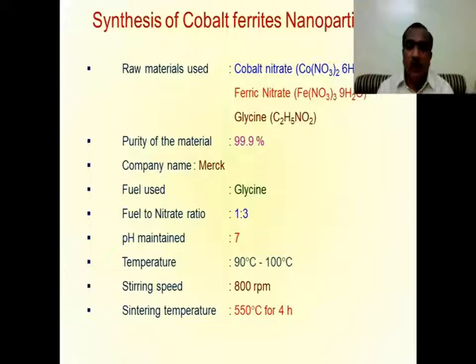We prepare this cobalt ferrite in nanoscale dimension by using the Sol-Gel autocombustion method. There are different methods for the preparation of cobalt ferrite nanoparticles. There are wet chemical methods like chemical co-precipitation, microemulsion, Sol-Gel, etc. Sol-Gel autocombustion is one of the best techniques for the preparation of nanoparticles of ferrite. The raw materials used in this synthesis method are cobalt nitrate, ferric nitrate, and glycine. Glycine is used as a fuel for the combustion process, and all these raw materials are of AR grade, 99.9 percent pure, and they are purchased from Merck.